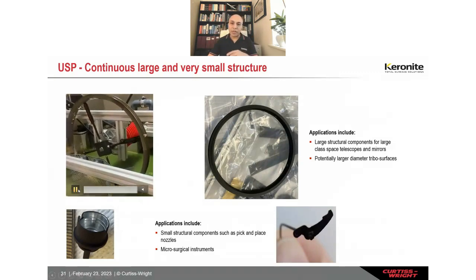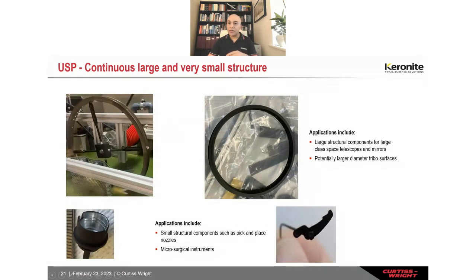And the result here is, you can see this one here, a fully coated wheel. And we extensively analyzed it in terms of optical reflectance, adhesion, and other characterization techniques. And the coating, in fact, is very similar to one we would have otherwise coated using a standard dipping process.